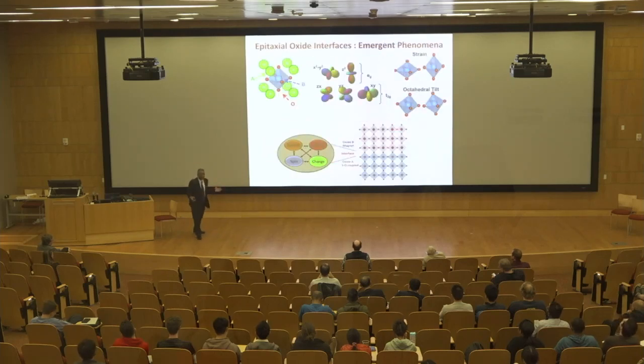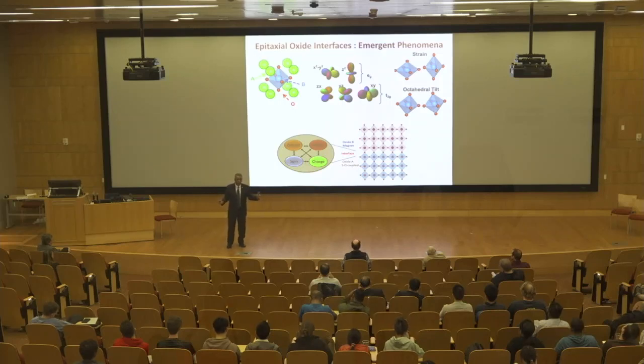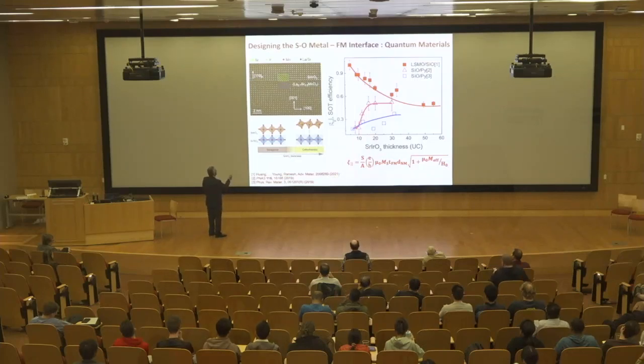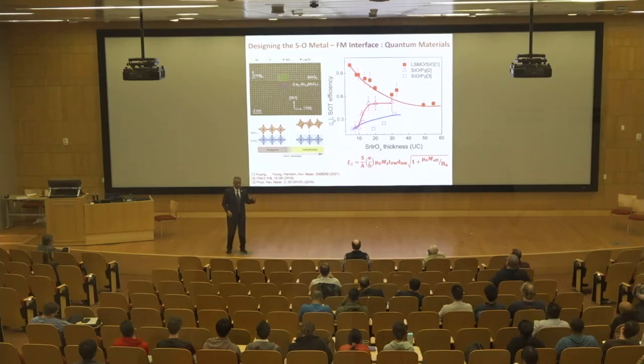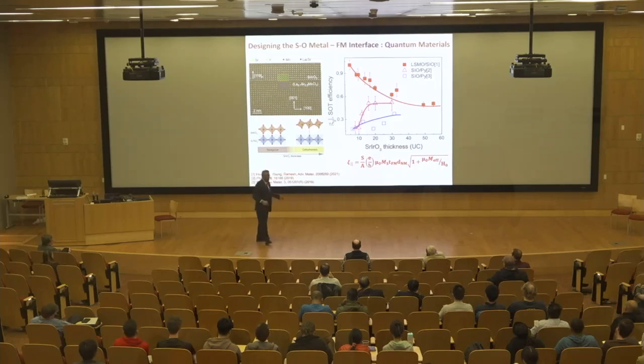Okay, so we went back to our standard game plan, which uses epitaxial interfaces where I can manipulate not only the electronic structure, but the spin structure and the lattice at the same time. And so we grew one set of materials, in this case, lanthanum strontium manganite is a ferromagnet, and strontium iridium oxide, which is a very, very interesting topological insulator, which has some very interesting electronic structure effects. And you can see that this efficiency is changing significantly as I reduce the thickness. It is actually going up as I reduce the thickness below 10 unit cells. If I make it polycrystalline or with a normal ferromagnet, that efficiency actually is lower.